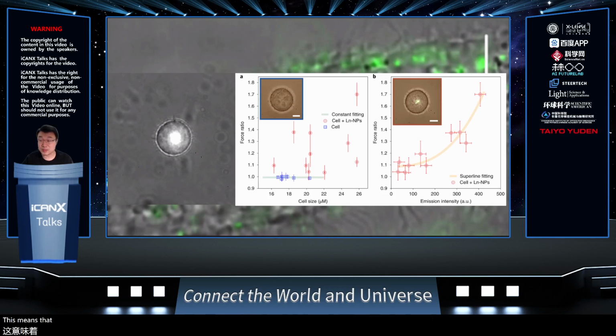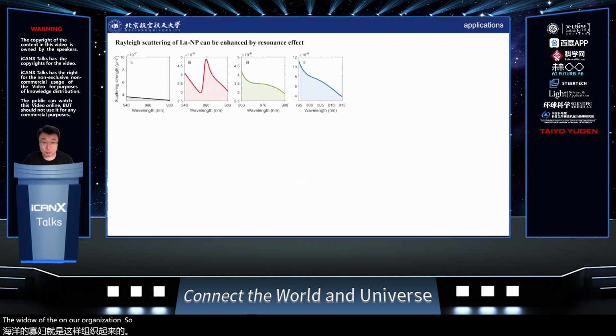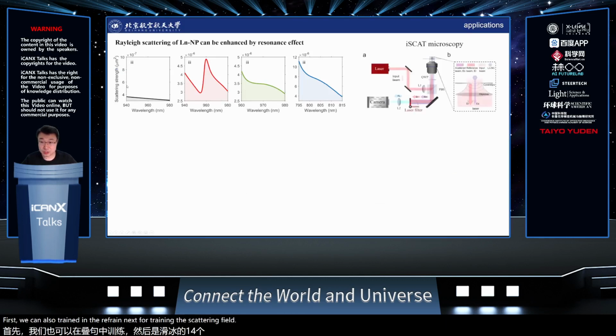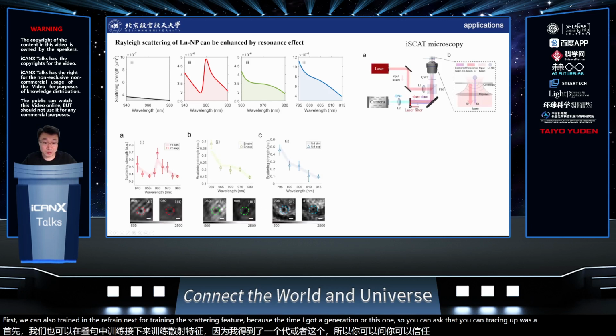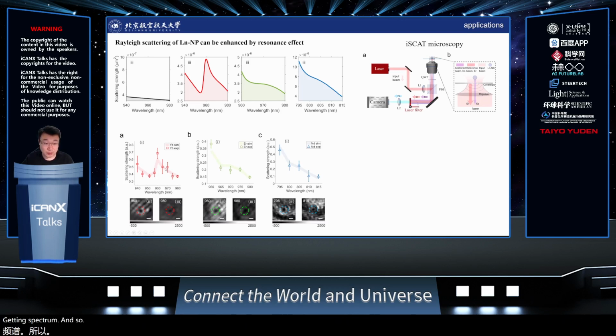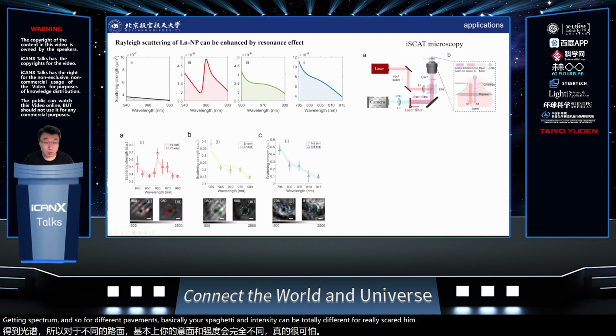It means that if you dope this nanoparticle inside the cell, you can even control each individual organelle. And apart from just increasing the force, we can also tune the refractive index to tune the scattering feature. Using iSCAT, you can trace this value, and you will see that for different types of nanoparticles, we can change the scattering spectrum. For different wavelengths, your scattering intensity is totally different. For normal Rayleigh scattering, it just keeps decreasing, but for this one, you can tune it.